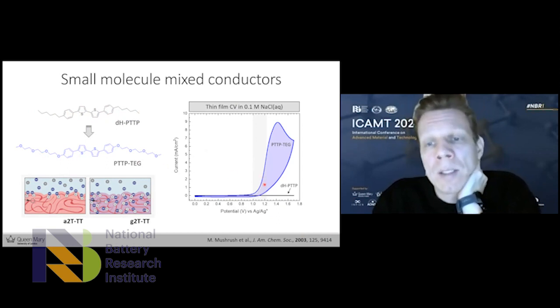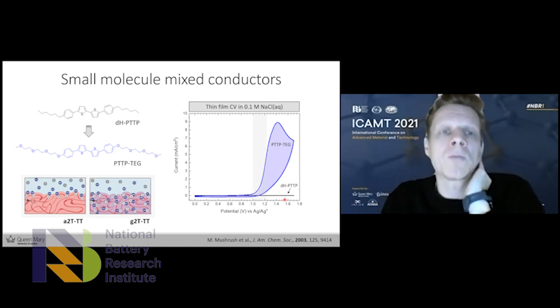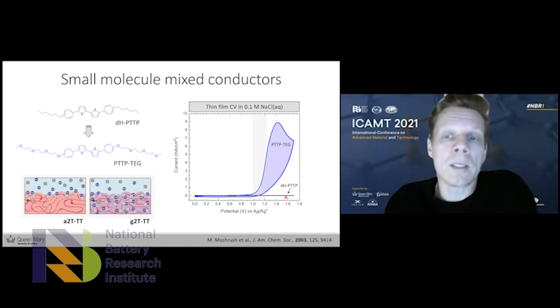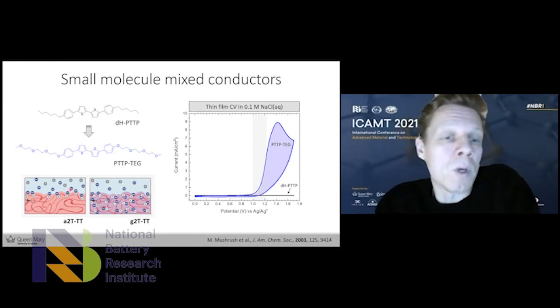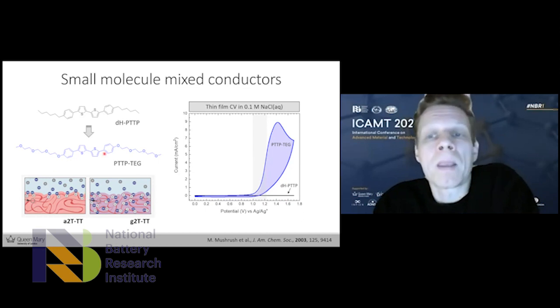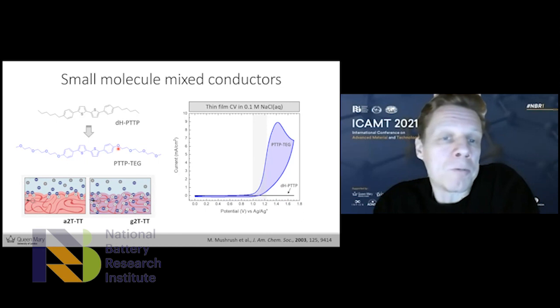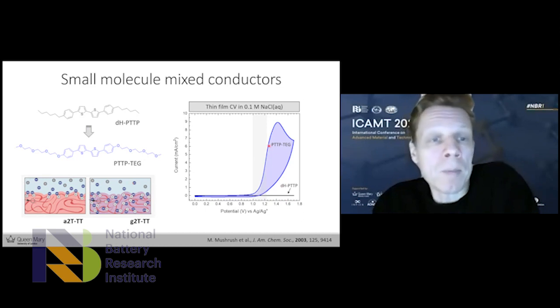And you can see here in the cyclic voltammograms conducted in aqueous electrolyte, the original material does not switch. We cannot electrochemically switch that in aqueous electrolyte. In agreement with our previous studies, we only get accumulation of charges at the surface. But when we make it much more hydrophilic, much more polar, we can see the ions penetrating into the bulk of the film, and now we can do an electrochemical switching of this material in aqueous electrolyte.